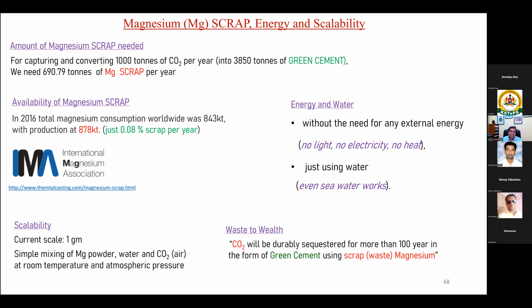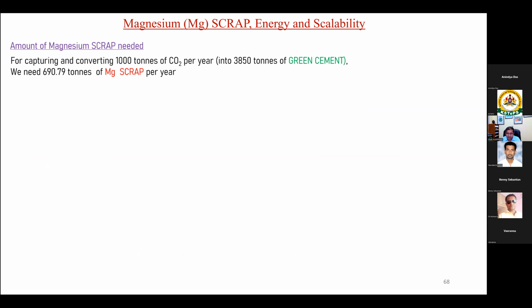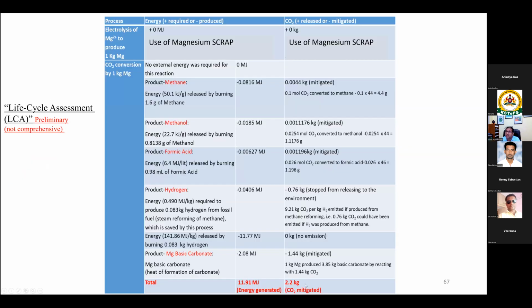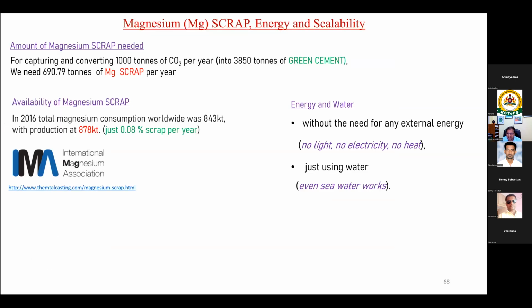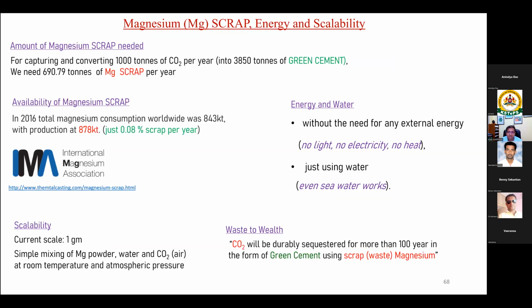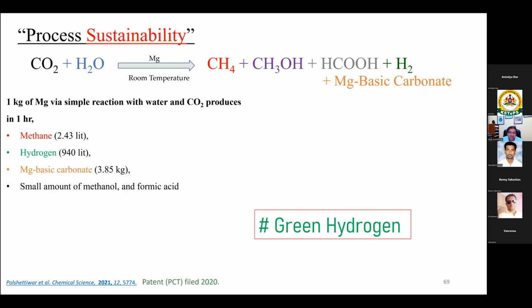So ideally, if you produce 1 kg of cement in a conventional way, you emit around 2.5 kgs of CO2. Here it's the other way around: I produce 3.85 kgs of cement from 1 kg of magnesium, and I mitigate 2.2 kgs of CO2. Just the opposite. So you can imagine if every cement industry starts using this - because cement industry is the biggest polluter, in addition to steel - they can use this process.